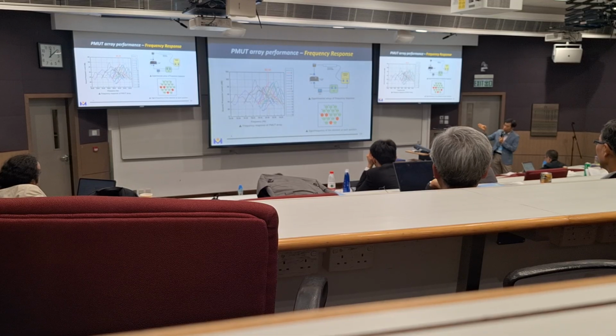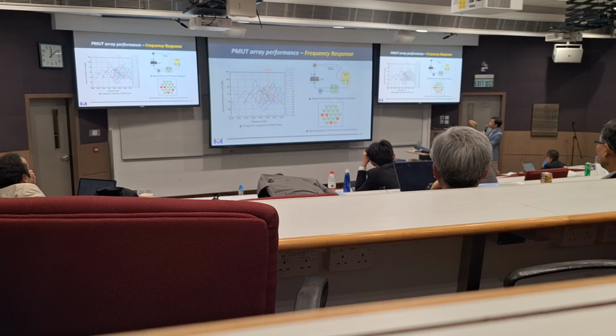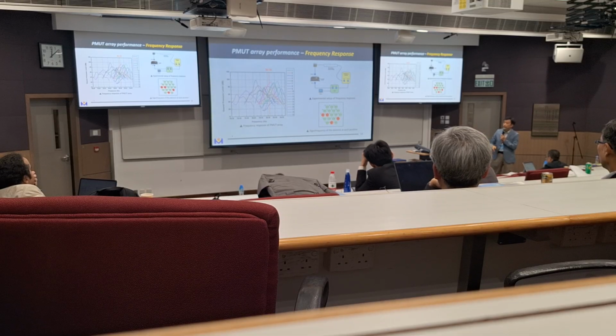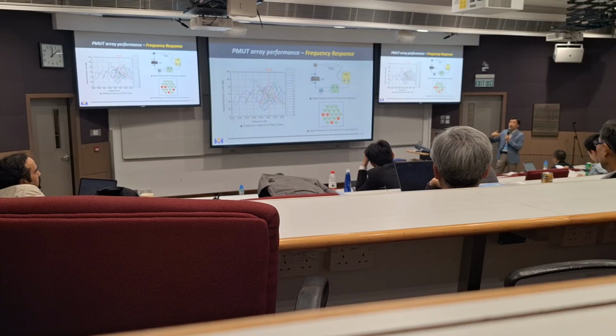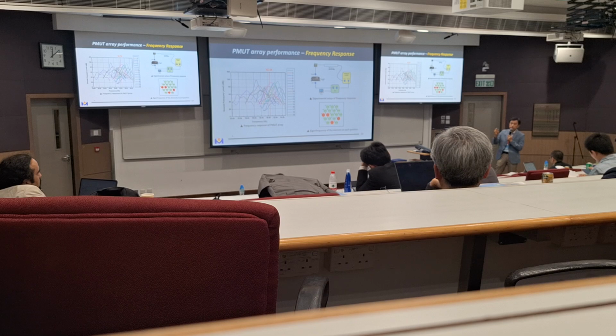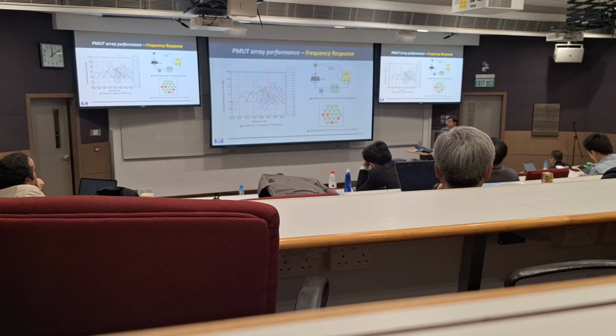So for example, on the left-hand side, you can see the resonant frequency is away from our design frequency, 60K, by almost 10 kilohertz. If you want to do beamforming, it's already far from what we can do because the frequency difference is too large. So in the end, we can only choose some of them that are good enough, with a resonant frequency close enough to do the final verification.